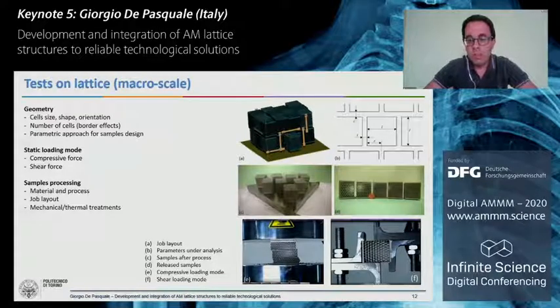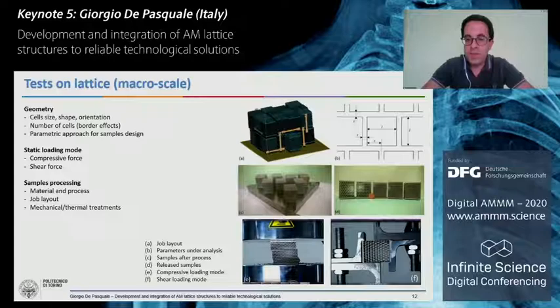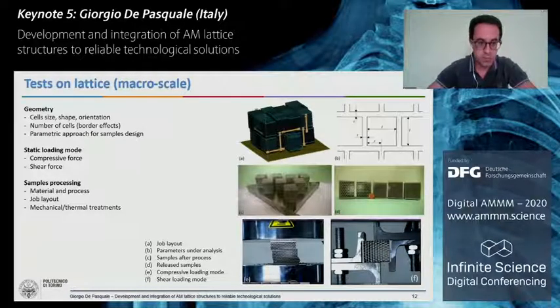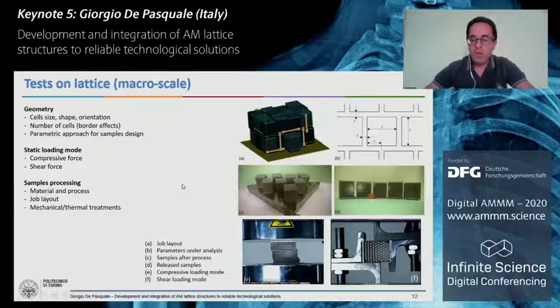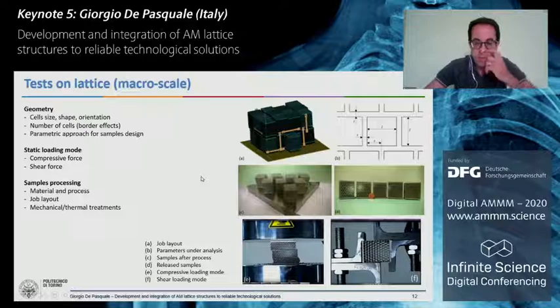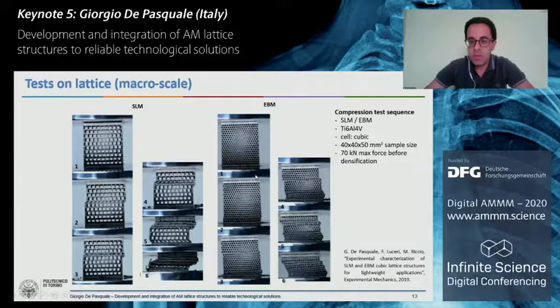On the top left, we have an example of the layout of our machine chamber filled with different kinds of samples with different orientations. Then the printed samples, the released samples, and on the lower line, we have two frames of compressive and shear tests on lattice structure samples. Of course, here we also have other influences on the results, for instance from post-printing thermal treatments on the samples.